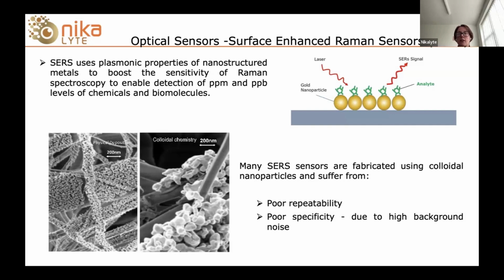Many SERS sensors are available on the market, and most of these are fabricated using colloidal nanoparticles, which have their place and can work quite well. I've shown an image here of a typical colloidal substrate, and what you can see is the problem I mentioned earlier about agglomeration and nanoparticles sticking together in solution. When they're either evaporated or dropped onto a surface, they tend to stick together around the edge. So you get this very non-uniform coating when a SERS substrate is manufactured using colloidal nanoparticles. The problem with this is that it can lead to poor repeatability because you're getting very different densities of nanoparticles on the surface.